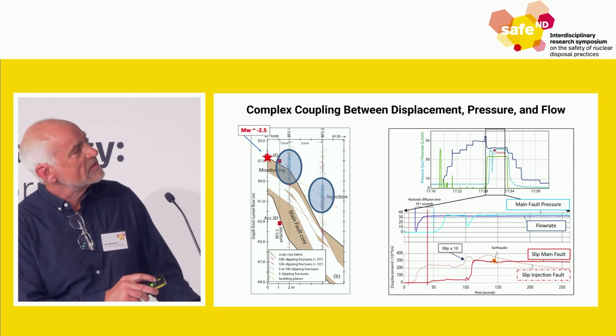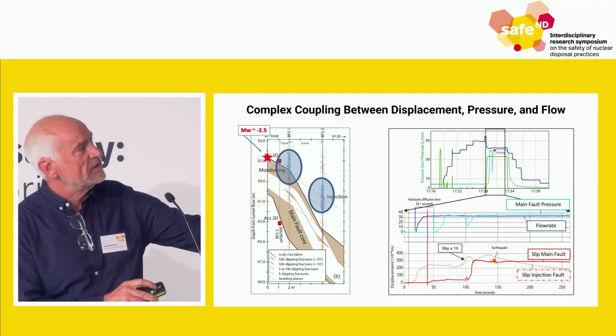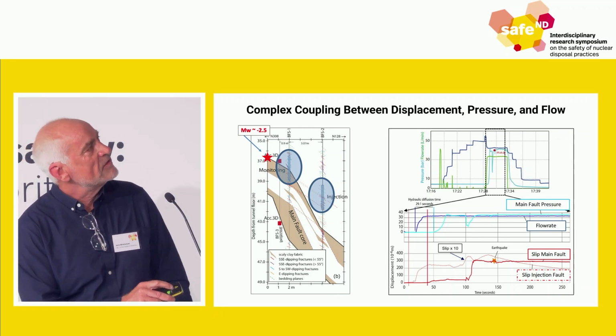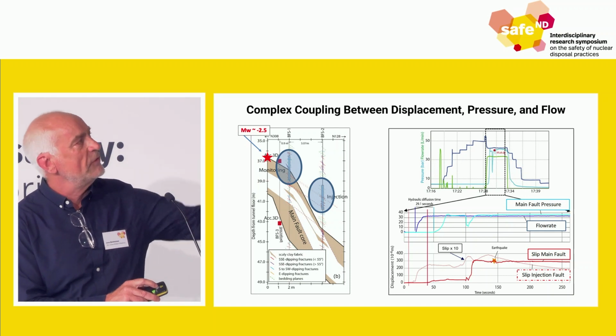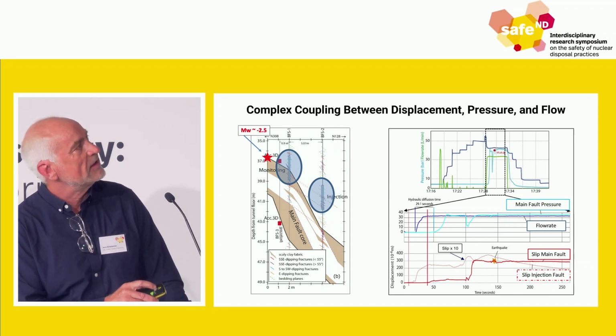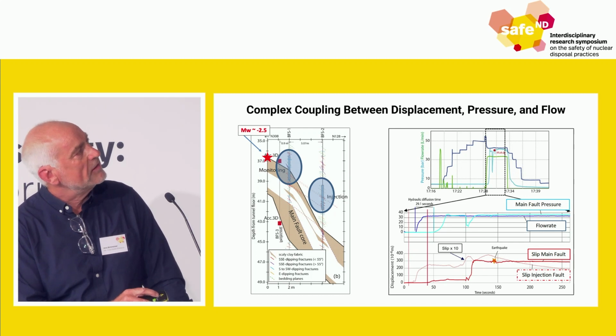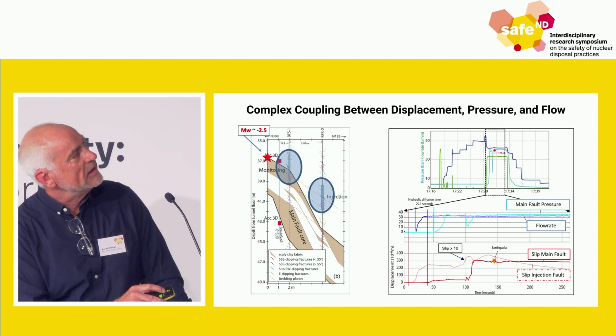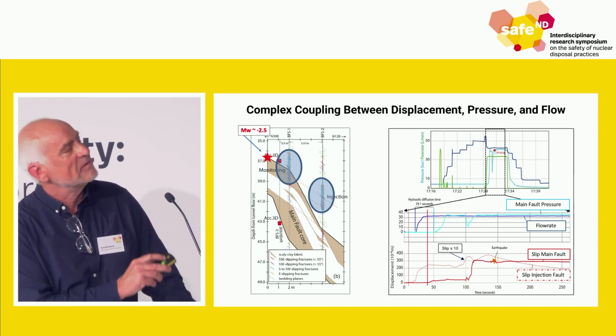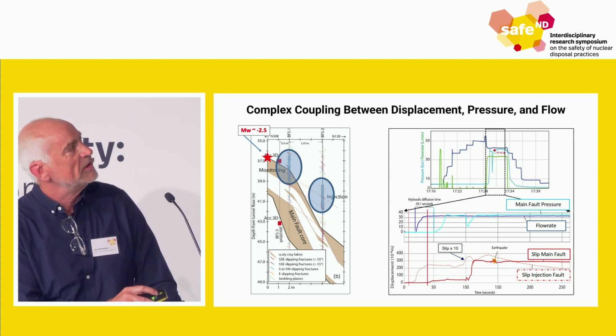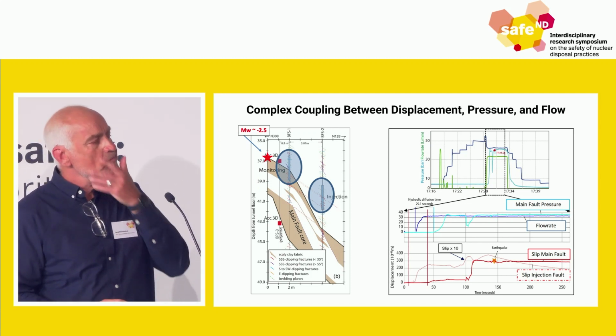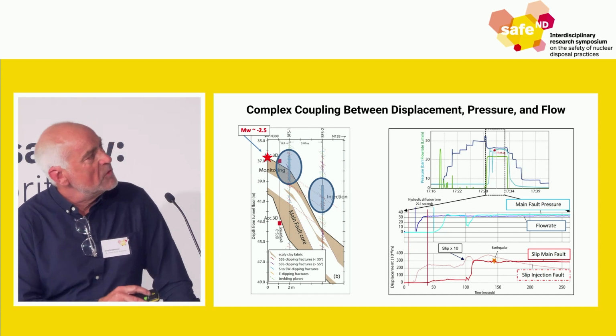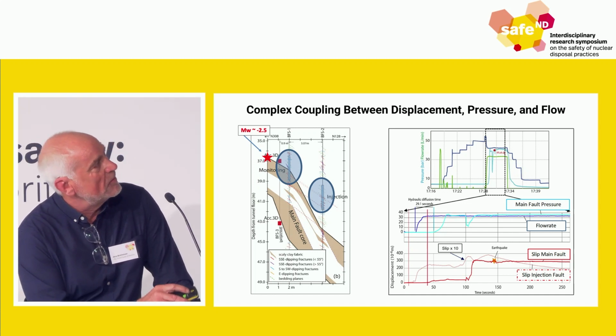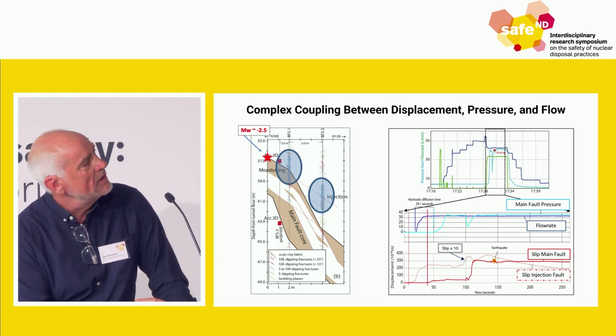We got this sudden pressure drop because permeability was developed, and then the system wants to push fluids to keep the pressure at that level. In light blue, you see that now we got breakthrough here, and a little later another pressure drop as if something further out happened in terms of permeability generation, and then this earthquake. We could look even more closely into just this sequence when we generated permeability.